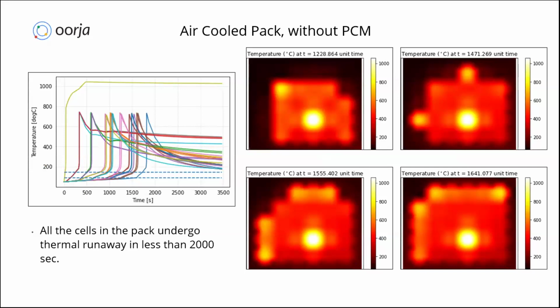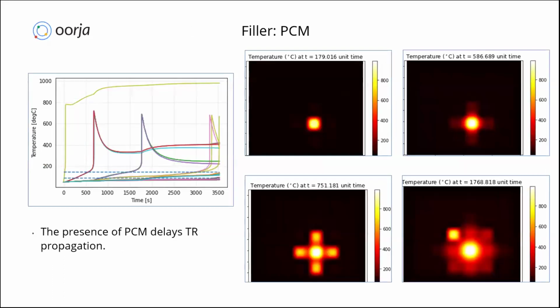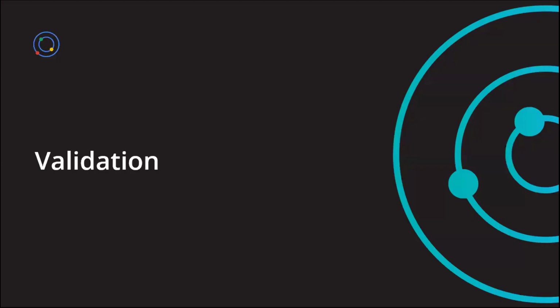So here in this case, you can see that this is the air cooled pack without any PCM, wherein all the cells undergo thermal runaway. Whereas when we started using PCM for this particular design, you can see that the thermal runaway got delayed based upon the cell to cell spacing used. We have also seen some customer use cases wherein they used this PCM inside the pack, and because of that they could get rid of thermal runaway altogether, based obviously upon the pack design they have along with the phase change materials itself.